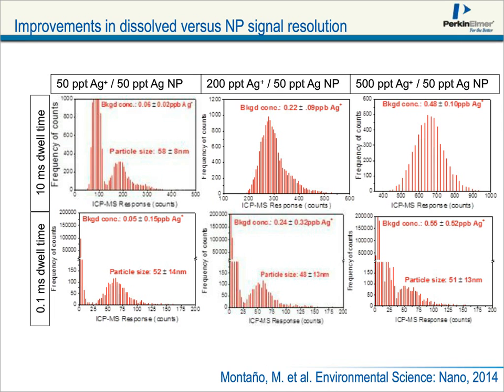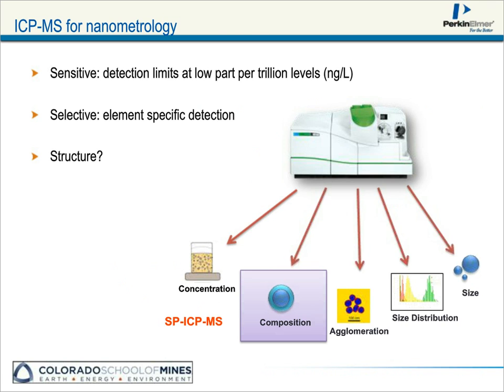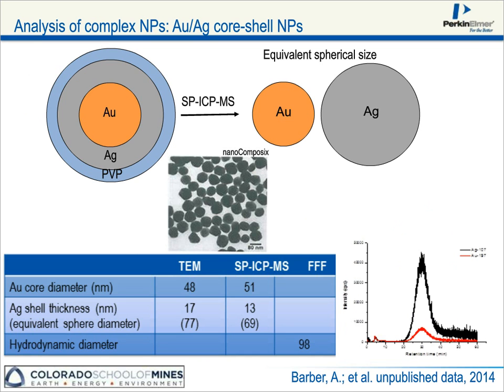Now, if we think about how we might tease a little more information out of this approach of single particle, let's think a little bit about the composition, or I should say the structure of the particles. If we combine some of these dissolution experiments with single particle ICP-MS, how might we learn more about how elements are distributed in nanoparticles? We're studying this by starting out with a fairly simple, well, I guess it's a complex material, but we're using a core shell particle. It has a gold core with a silver shell and a PVP stabilizer coating. Of course, ICP-MS doesn't show us anything about the PVP, but it does give us the equivalent mass of gold and silver in a particle.